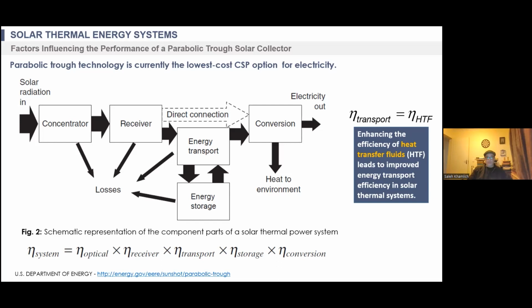In our case, as I mentioned, we are focusing mainly on the transport because we found that this parameter is one of the most important parameters nowadays. Because I believe scientists and engineers have done a lot in terms of the optics, the receivers, and also the conversion, but the storage also needs a lot of enhancement, of course. So the efficiency of transport is equal to the efficiency of the heat transfer fluid. And that is the reason why we decided to work on nanofluids in order to create highly advanced heat transfer fluids, which are nanofluids.